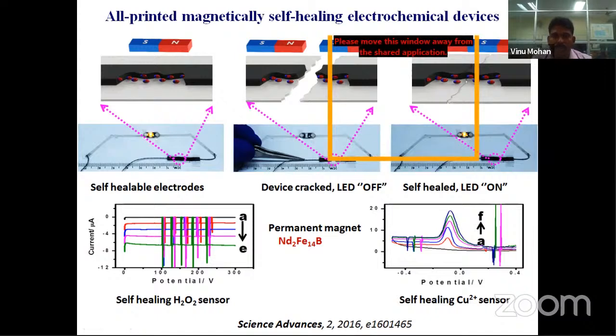So if you damage completely, not only the electrode but the substrate also, if you are cutting with a scissor, from even 1 mm distance, the self-healing can happen due to the magnetic attraction of the two different traces. Here you can see we used it for H2O2 sensing as well as Cu2+ sensing application. During the sensing, we damage it, basically using a scissor to cut the electrodes multiple times, but still we can perform the electrochemical analysis.